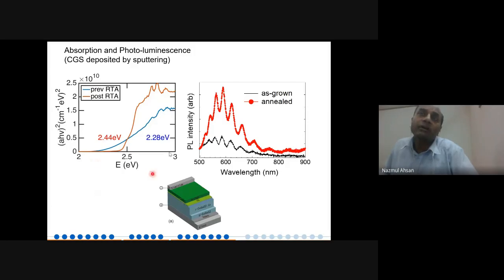This kind of material is very tricky because sulfur's vapor pressure is very high, and it is very tricky to make in sputtering. So we spend most of our time designing the sputtering system, having co-deposition sputtering with multiple guns, co-depositing them. One of our main challenges is how we can make high quality CGS without breaking the vacuum environment. So our target is to make the sulfurization, all the process, inside the vacuum.